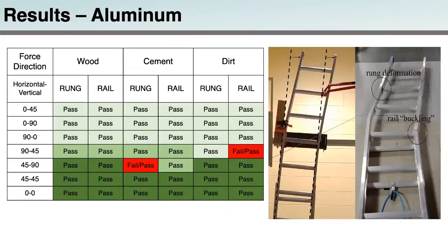So when looking at the aluminum ladder in comparison to the fiberglass ladder, the aluminum ladder performed significantly worse in comparison to the fiberglass ladder. The damage to the ladder was a lot more obvious. Initially, we thought we'd be buying 42 different aluminum ladders for each test. However, this wasn't the case.